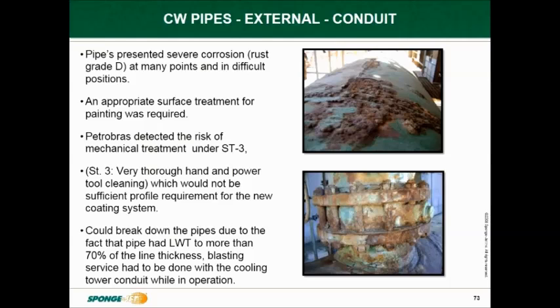Petrobras detected a risk of mechanical treatment, which is hand grinding and under an ST3 standard, would potentially remove too much metal and could break down the pipes due to the fact that it was extreme corrosion and it was apparent to more than 70% of the wall thickness. This service had to be done whilst the cooling tower was in operation. Petrobras requested SpongeJet Global, the contractor, to perform the SpongeJet abrasive blasting on this particular project.